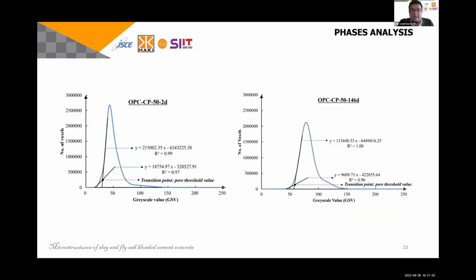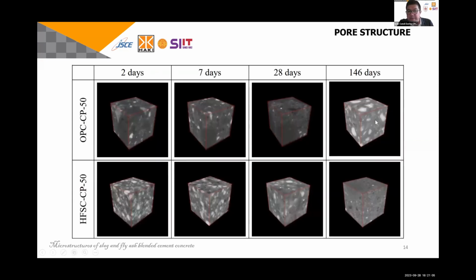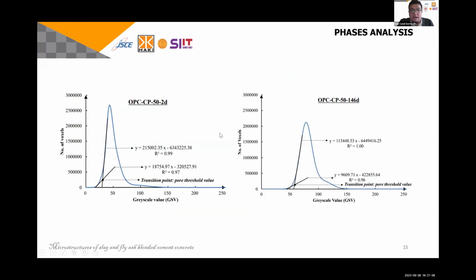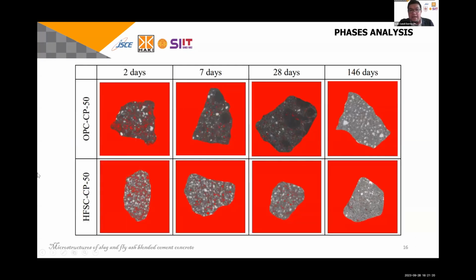And then for the pore structure, using the same VOI, I have a histogram here, and I try thresholding to separate between solid and void. As you can see here, the red one means void, and the gray up to white means solid. Of course, in maybe slice 1 up to 3, we will have a very high porosity in both specimens, OPC and also fly ash.